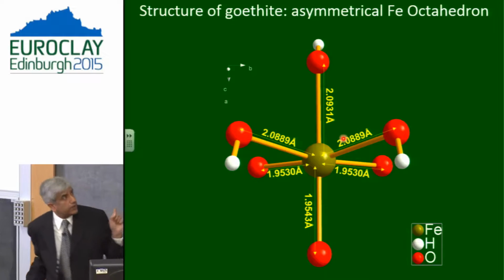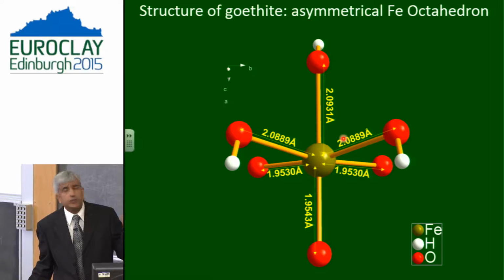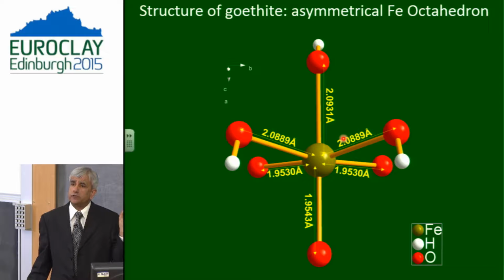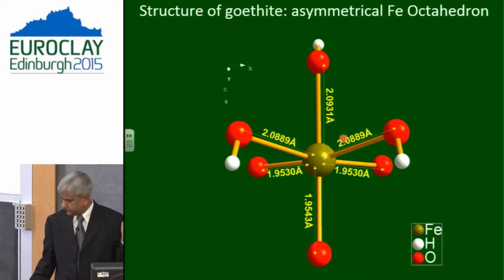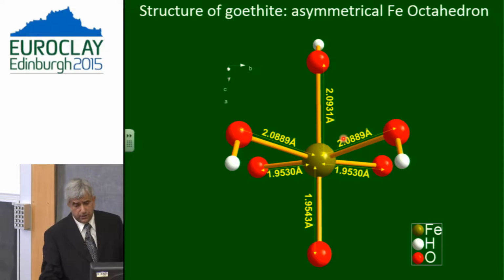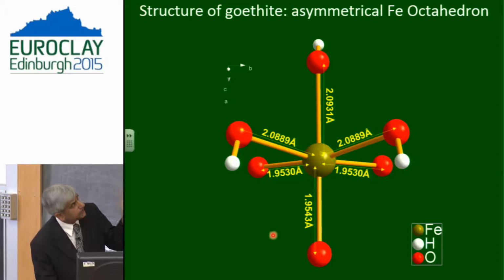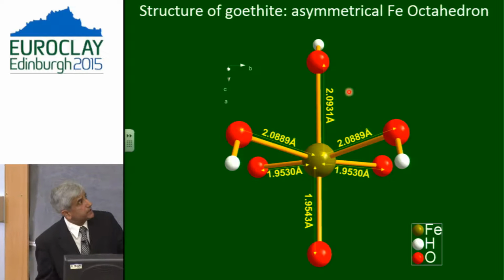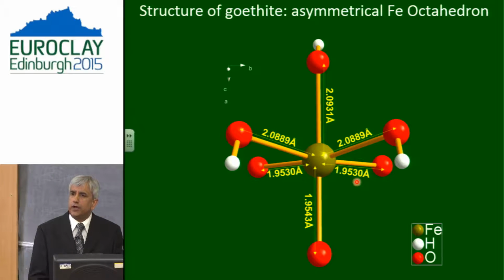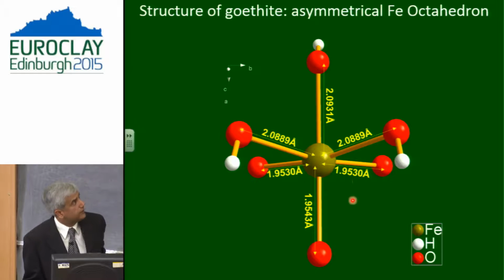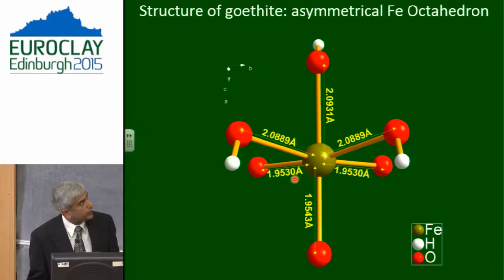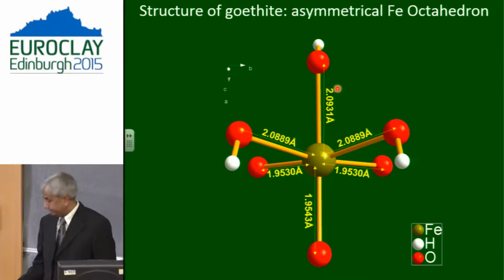Just a very quick demonstration of what happens to the actual structure of goethite with the substitution of these metals. If you look at the structure of goethite here, you can see that in the octahedra, the distance between iron and oxygen or iron and hydroxyl is different. You can see the iron-oxygen distances are about 1.95 angstrom, and in case of iron-hydroxide, the distances are about 2.09.